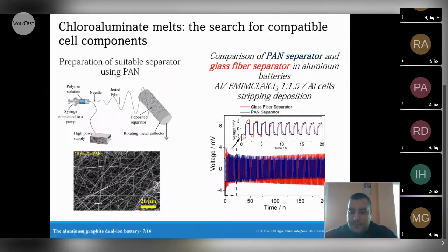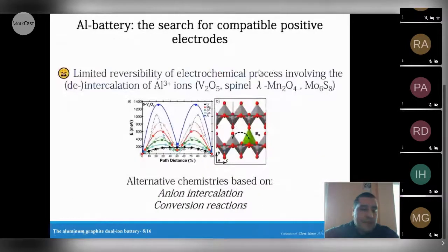melt. And as you can see from the electrochemical results of the stripping deposition process of a symmetrical aluminum cell employing this electrolyte, we can efficiently strip and deposit aluminum with a limited overvoltage between the deposition and dissolution process. And consider that the overvoltage reported for this aluminum cell is close to the stripping deposition overpotential reported for a lithium system utilizing ionic liquid-based electrolyte. Clearly, the reactivity of the electrolyte used in aluminum system is one of the main issues.